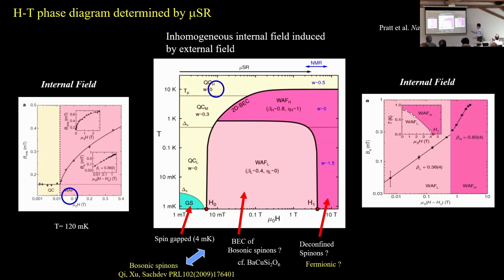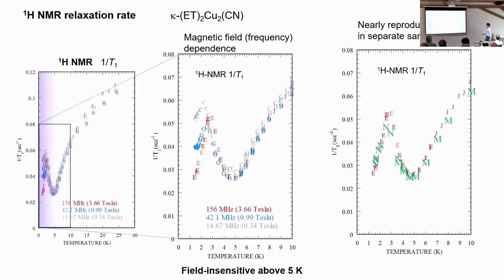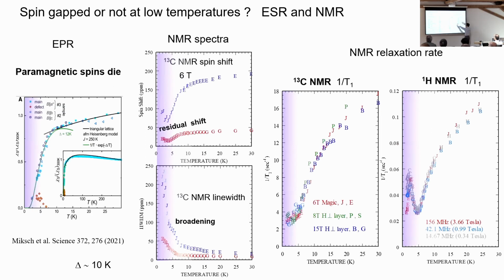Okay, both NMR relaxation rates go to lower values and the susceptibility decreases at 6 Kelvin, but below 6 Kelvin something happens. Something anomalous, a phase. The anomalous phase can be detected differently at the proton NMR and the carbon site.